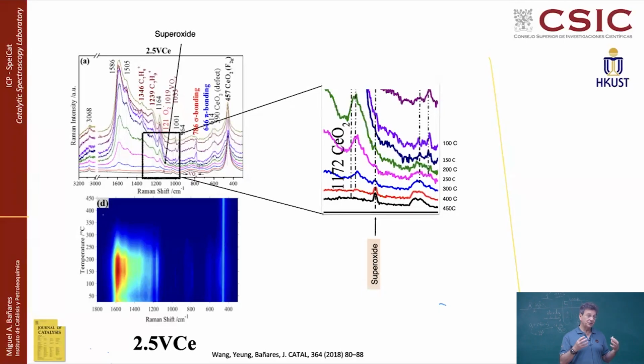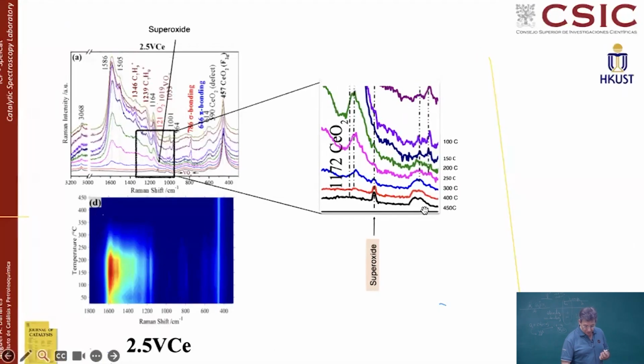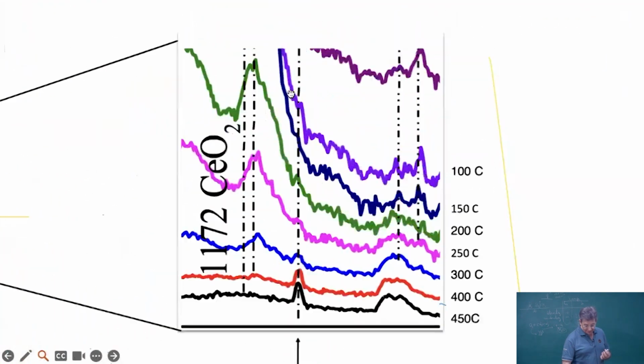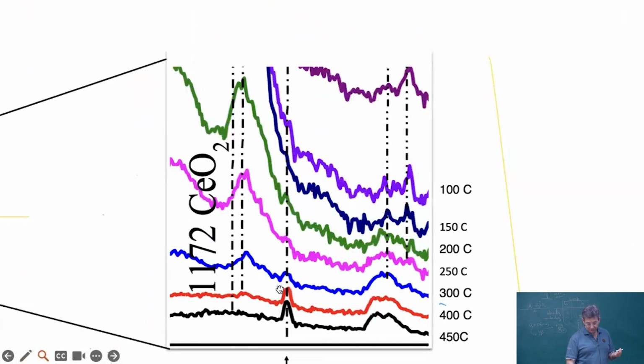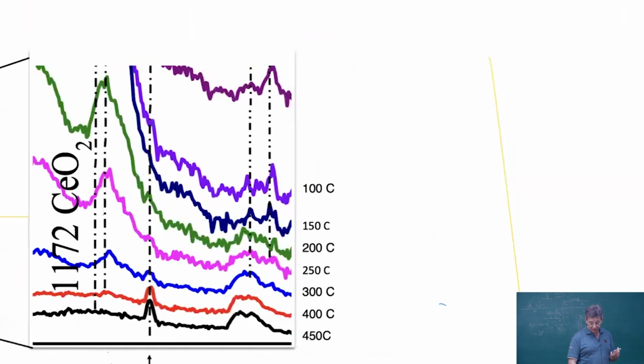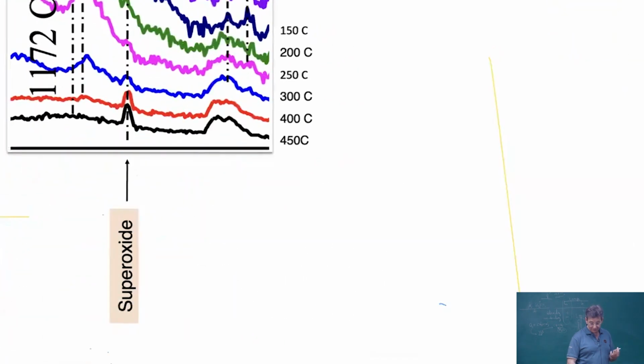Because at high temperature, this oxygen adsorbing on cerium-3 sites will reoxidize it, and then it will become lattice oxygen, oxide ion, and you no longer see the superoxide. So you never see superoxide at high temperatures. And in this case, we are observing superoxide at high temperatures. When you get rid of the hydrocarbon deposits, then you start to see that you have this superoxide at the surface. But that's normal because now we are dealing with a system that we already had discussed,